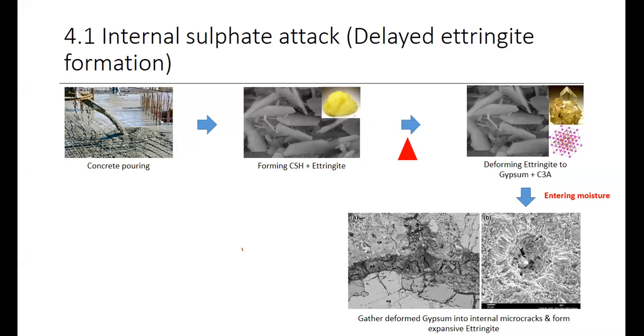I already told you that ettringite is an expansive product, and the expansion is similar to what happens during the freezing of water in a glass water bottle. The same thing happens here. The concrete, with time, gets hardened. The concrete has already hardened, but due to the ingression of moisture, it now develops some expansive product inside the concrete. With that pressure, concrete can get damaged and can develop cracks. Since it happens at delayed ages, we call it delayed ettringite formation. That is the mechanism of ettringite formation in delayed stages.